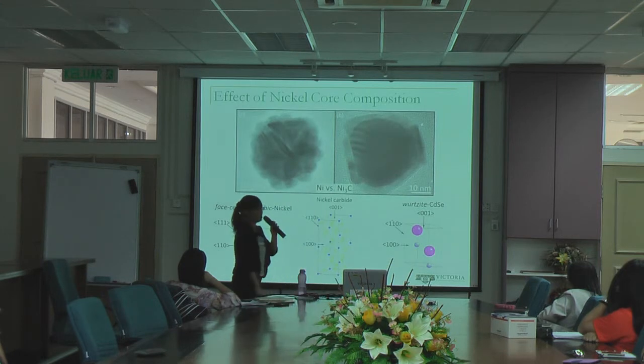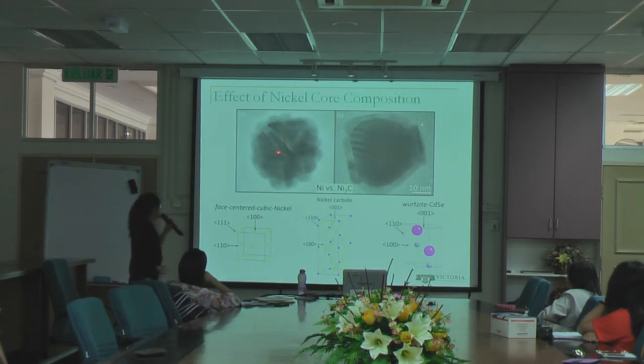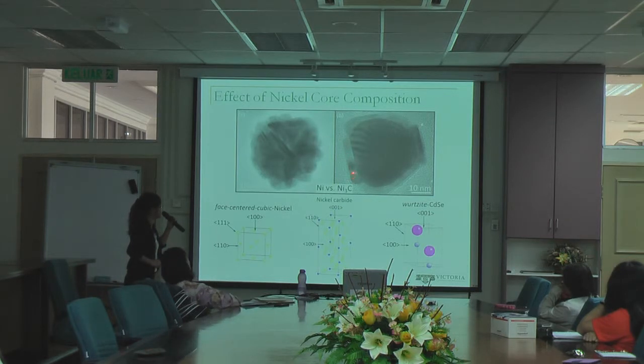So next, another interesting comparison will be between nickel and nickel carbide. As we have discussed before, for nickel, due to the large mismatch between the crystal structures, face-centered cubic nickel and hexagonal wurtzite, we tend to get cadmium selenide that has small contact area with nickel as well as small size. But what happens for the nickel carbide is kind of opposite, because we are seeing that the cadmium selenide grows into a much larger size domain, and also it tends to have a much higher contact area with the nickel carbide.